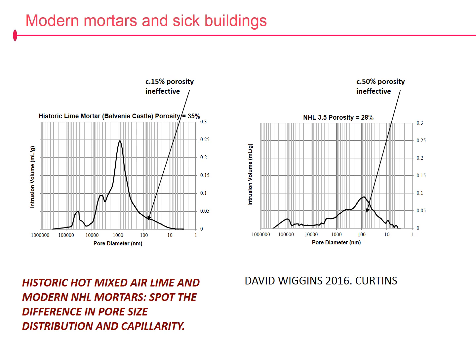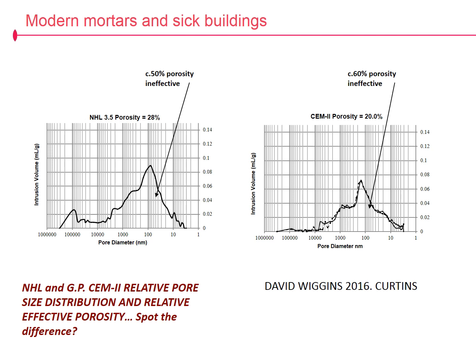So what's going on here? Drawing on David Wiggins's incredibly important research, we see that typically a hot mixed lime-rich mortar, air lime or feebly hydraulic lime, has a very high density and proportion of 1 micron pores, or in the vicinity of capillary active pores. Compare that on the right hand side to the pore size distribution in an NHL 3.5 mortar, and we see very few of those pores and far more pores which are ineffectively porous. And when we put that same graph alongside a graph of the pore size distribution of a CEM-II cement mortar, we see minimal difference in effective porosity between the two.